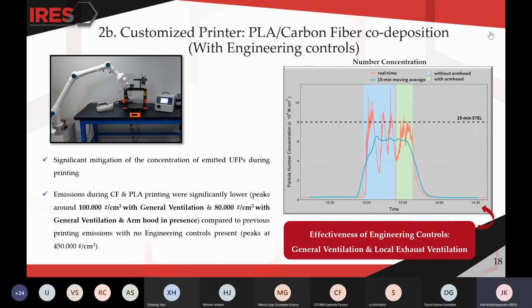We can notice that the 15-minute average ultrafine particle concentration was kept under the recommended limit during the whole process. Moreover, concentrations, as you can see, are much lower, with peak values being about 4 times lower than without engineering controls. So through using this setup, a significant mitigation of exposure was achieved.